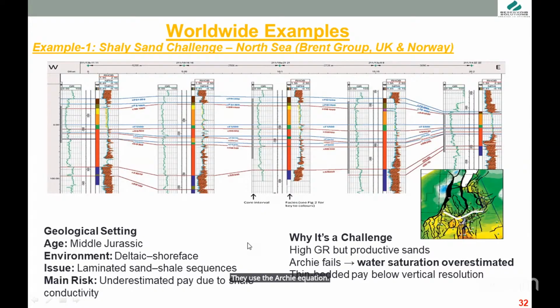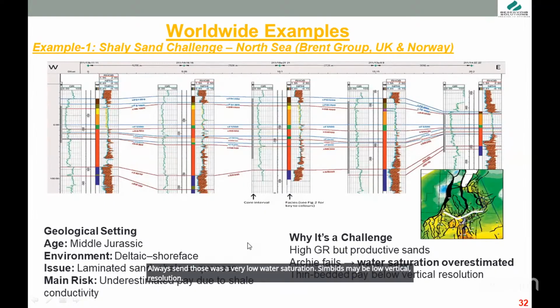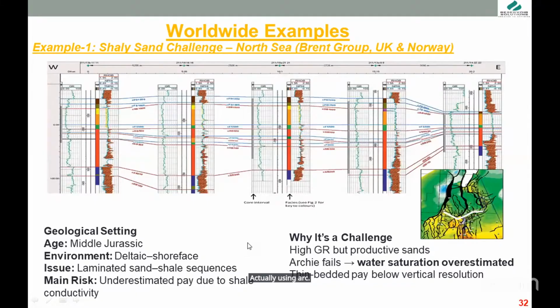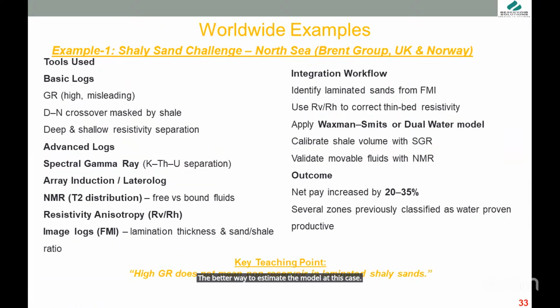Water saturation is overestimated. All this sand has very low water saturation, thin beds below vertical resolution. Actually, using Archie in a shaley sand model is the big mistake you will make. The better way to estimate the porosity model in this case is using Waxman-Smits or dual water model or Indonesian, just one of them. Waxman-Smits is better here because there is no core data for the calibration.